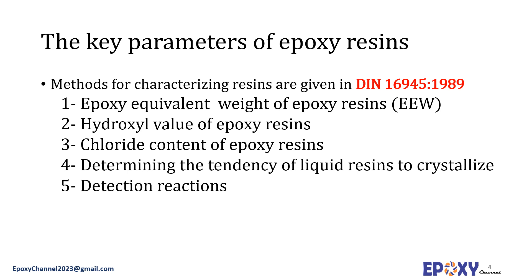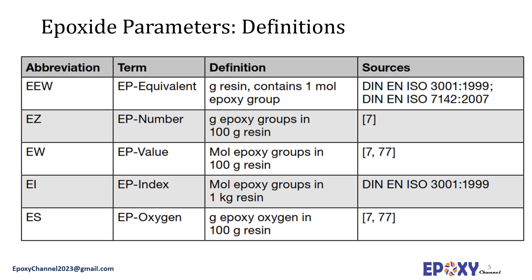When presenting an epoxy product, some parameters must be presented — some more general ones like density and viscosity, and some others are key parameters that must be presented in the TDS. The epoxide equivalent of epoxy resins should be presented, as should hydroxyl value, chloride content, tendency to create crystals, and detection reactions. An overview of the most common parameters and methods for determining them is given in DIN 16945.